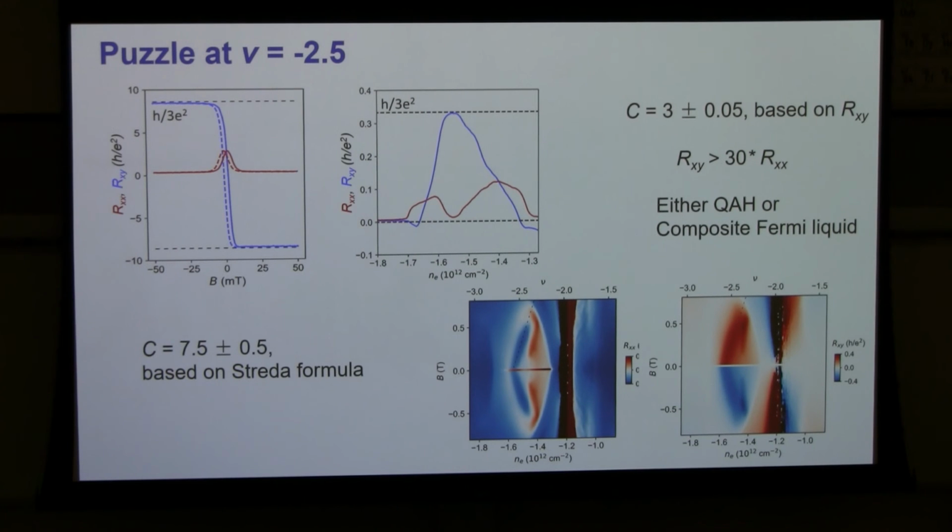Okay? Phenomenologically, it feels like when you increase the magnetic field, the volume of this flat band increases, and you need to put 7 electrons in there, but only 3 of them contribute to the transport. This is something we don't understand, but I believe this is the first fractional filling of a high Chern number quantum Hall topological flat band. Okay, question is why?